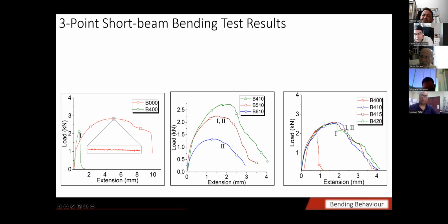Again, pre-sinter or after sintering? These are in the bulk form, so they must be sintered. After sintering, okay. Of course, because of the presence of iron boride phases. Sir, the presence of B4C particles is not going to influence the bending behavior very much, because the size ratio between the iron and B4C particles is so big that all the B4C particles do is sit embedded in the interparticle boundaries. So I don't believe they are going to change the mechanical response of the material.